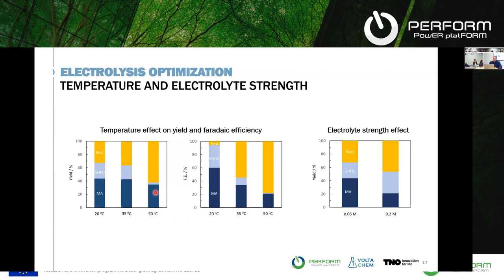When we increase the temperature, we lower the yield of the reaction considerably. So this is really pointing in the direction that we should operate at lower temperatures to have better conversions.